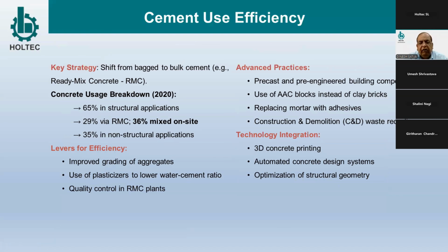Now, if we come to cement use efficiency, currently on a 2020 basis, 65% of concrete is used in structural applications, and 29% is via RMC, and 36% is mixed on site, which is a very crude way. So it is important that mostly it should be converted to RMC. And even in RMC functioning, quality control also needs to be improved so the exact design of the concrete is made without any excess cement or any other issues. Similarly, use of plasticizer to lower water cement ratios. Then correct size of the aggregates is very important.